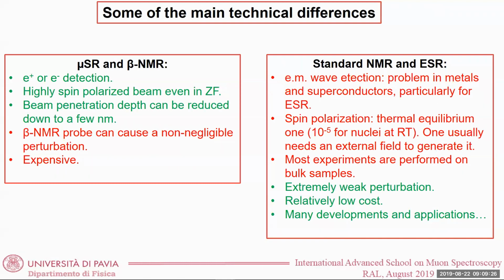Beta NMR is, of course, something in between, because in beta NMR you have to use also radio frequencies. But MUSR certainly has these two big advantages. And the other big advantage is that you have listened to Suter's talk yesterday on low energy muons. And with low energy muons or with beta NMR, you can conveniently produce a beam which can penetrate only down to a few nanometers and then study thin films of different materials. While typically, but it's not always the case, in NMR and ESR, you are working with bulk samples.